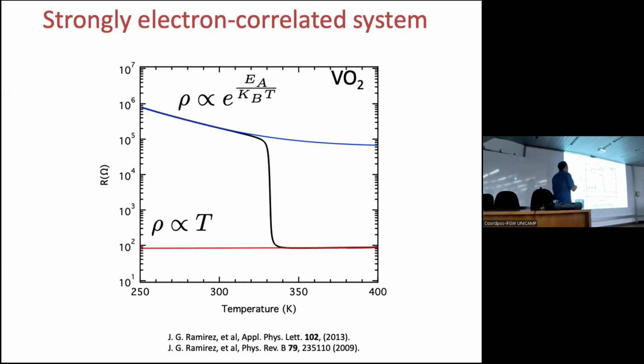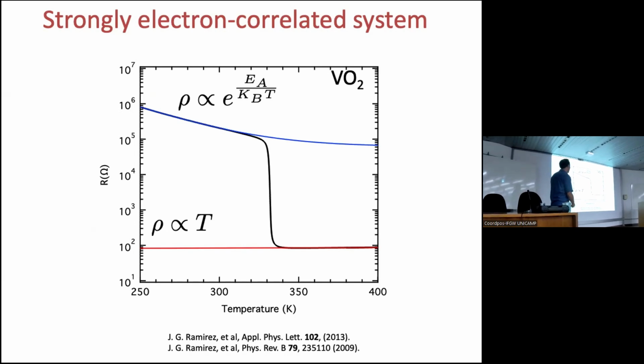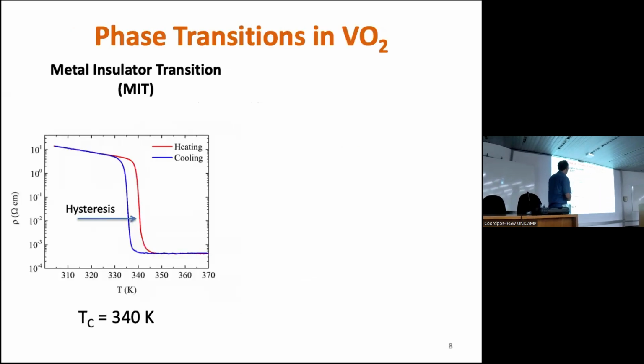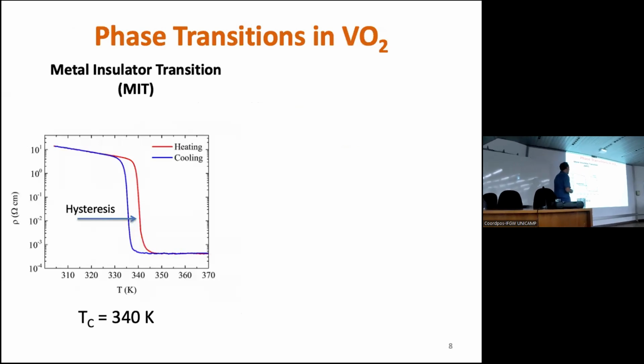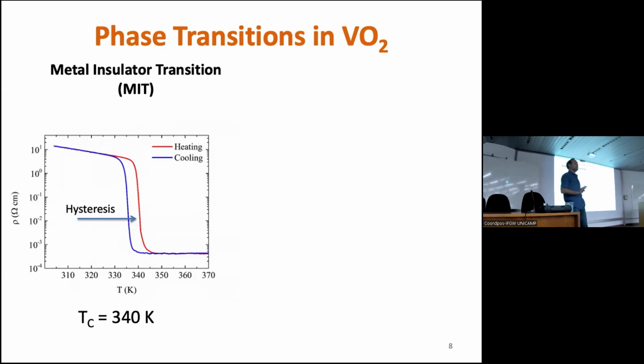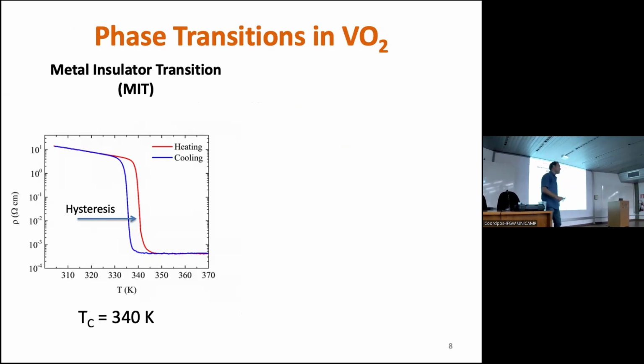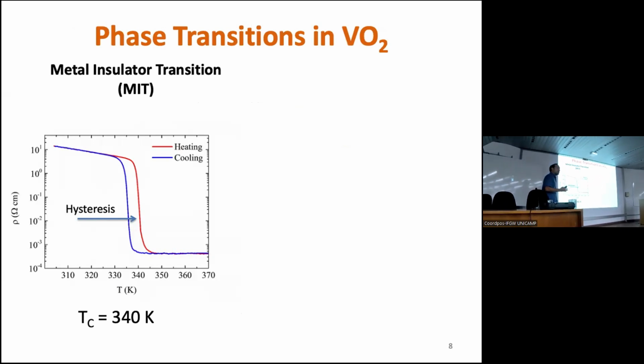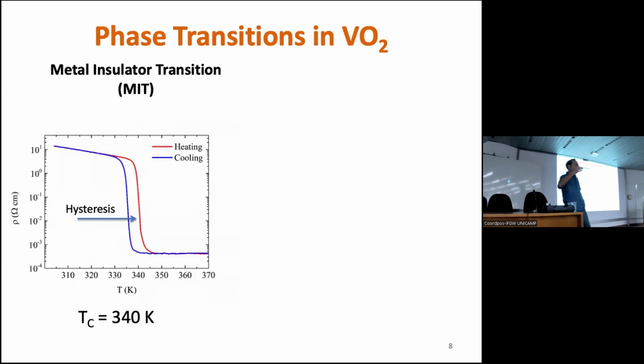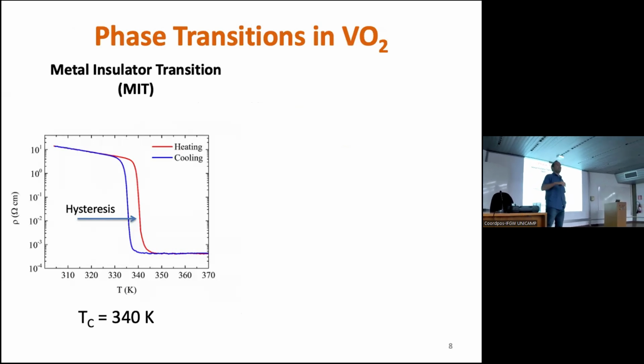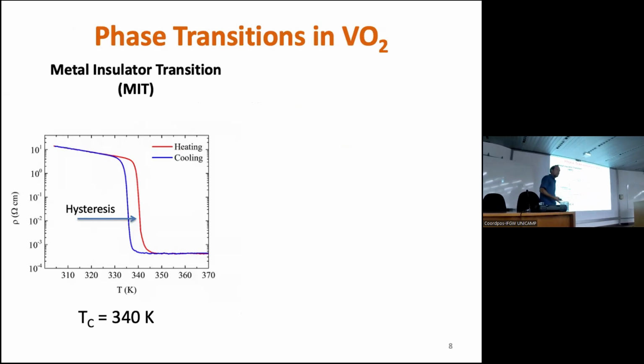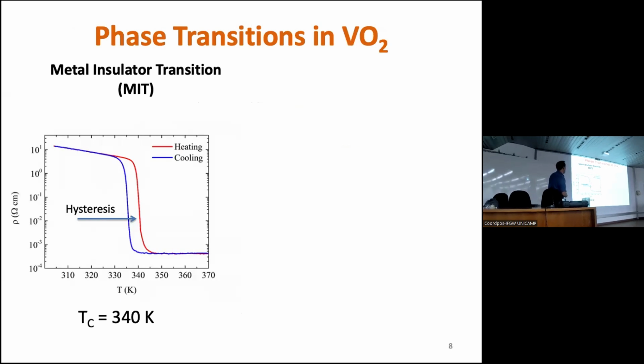But there are a lot of things to talk about. This is actually one of the reasons for the talk. So what happens in the material? It has a hysteresis. If you go back in temperature and reduce the temperature, the transition temperature is not the same, and this is because there is a phase transition. It's a first order phase transition. This hysteresis is a signature of coexistence of different phases. It's a signature of metastable states. Okay, so that's the idea of that.